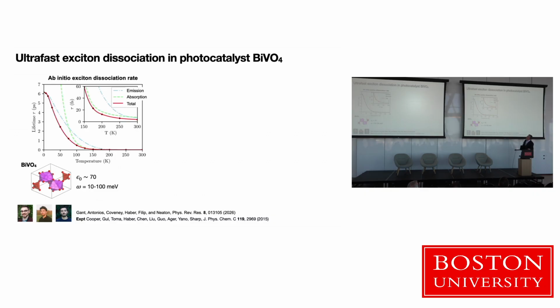And one of the things that's interesting is that even at zero temperature, there is a channel by which you can absorb a phonon and it will decay into an electron and hole. And you might be like, well, at zero temperature, there are no phonons available. Well, actually, this is an indirect gap system, and so there is a channel by which phonons can absorb and emit. Emit, not absorb. So for indirect gap systems, you have both of these emission and absorption channels available.